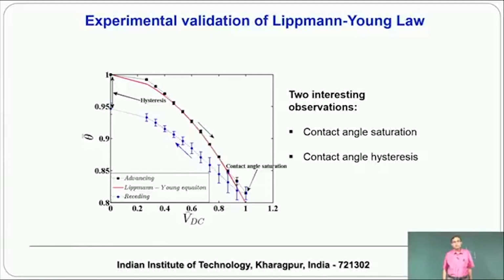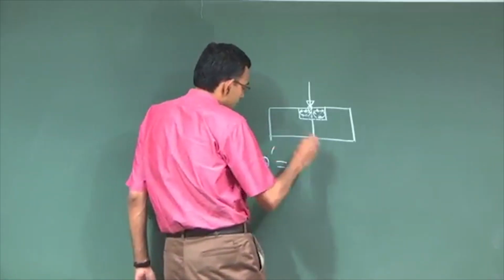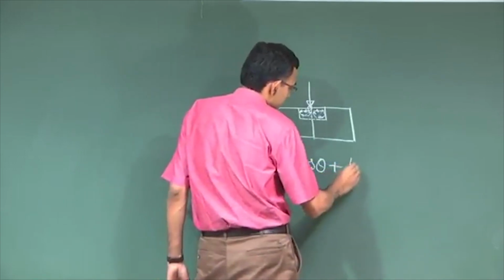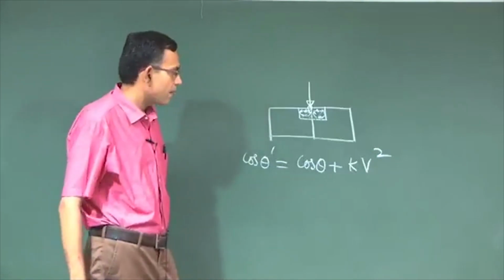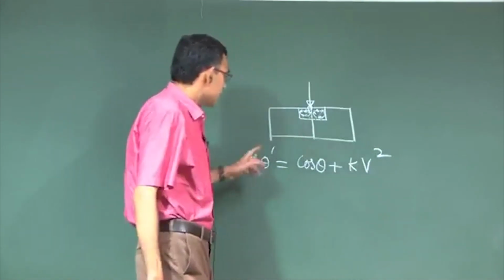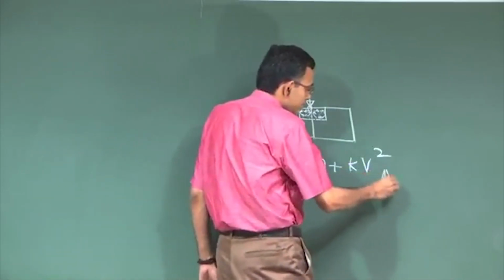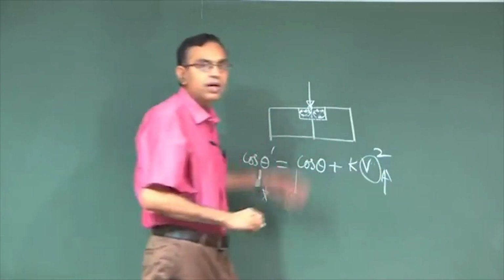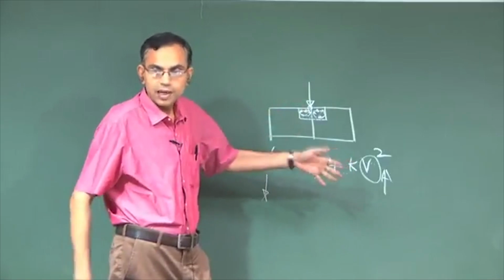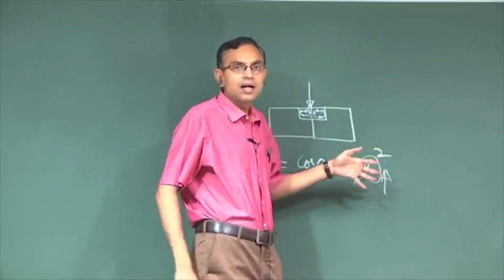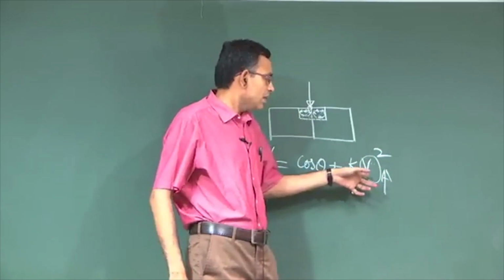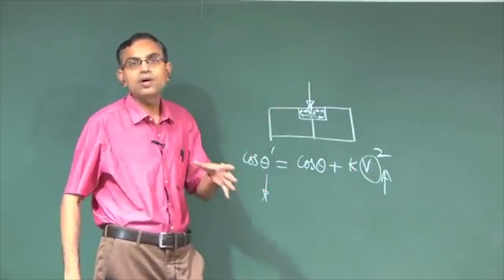So, now I will just briefly tell you about two very interesting observations. One observation is, let me write down the formula on the board so that we can explain these observations. Just for simplicity I am writing this. Now, this gives you an appearance that if you increase this voltage, the contact angle will go down and down and down like this, I mean forever, but it does not happen. It comes to a limit up to which if you increase the voltage, it does not come down anymore. So, the contact angle comes to a saturation stage.